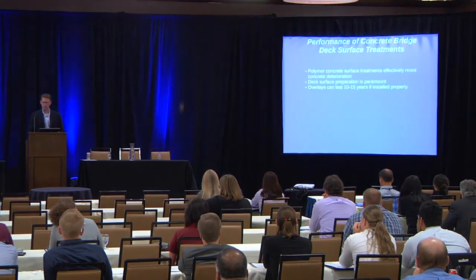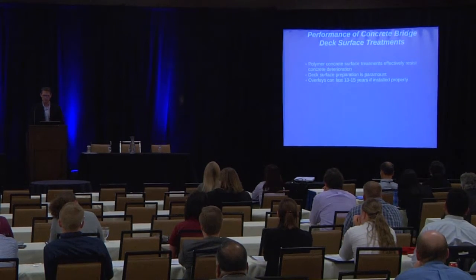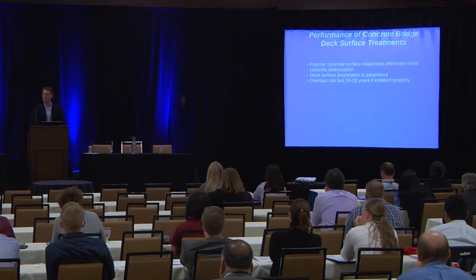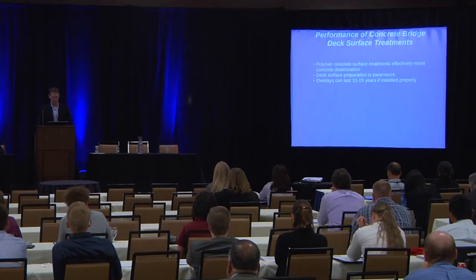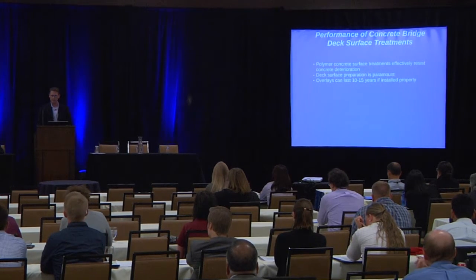In 2005, we studied the performance of concrete bridge deck surface treatments. We were already thinking about this in 2005, but we probably just didn't have them in service long enough. Now we're coming back and looking at this again because it's 10 or 11 years later. Even back in 2005, we began to see that polymer concrete surface treatments can effectively resist concrete deterioration. Deck surface preparation is key, and we do know that these overlays will last 10 to 15 years if done properly.